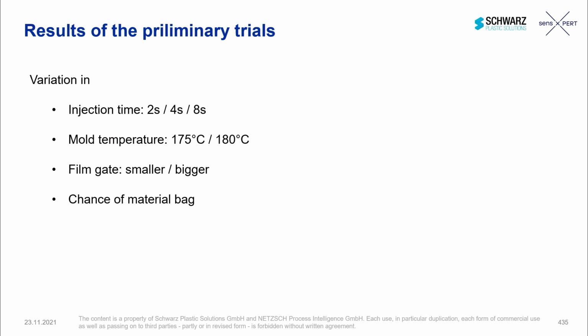So in that first trial which we did, we varied the injection time, equals injection speed, from the standard time, which would be 4 seconds in that sample. We doubled it, and we did 50% of it. So very strange extremes. And we also varied the mold temperature only a little bit, to see: do the 5 degrees have an influence? Or are we overdoing the whole thing?